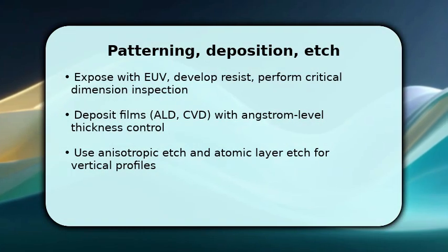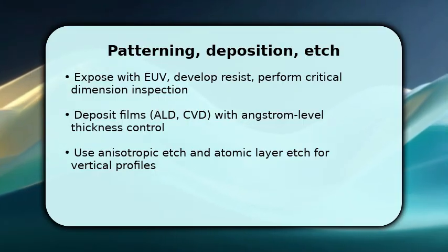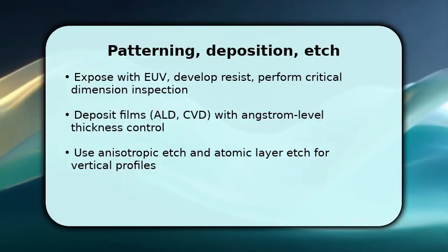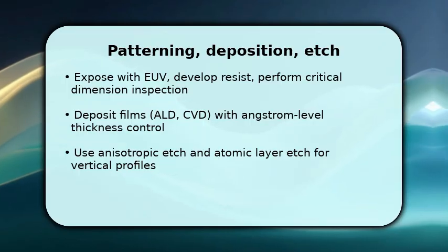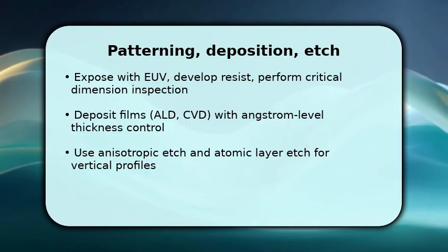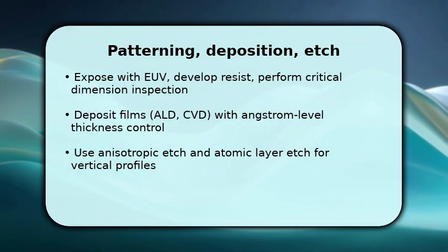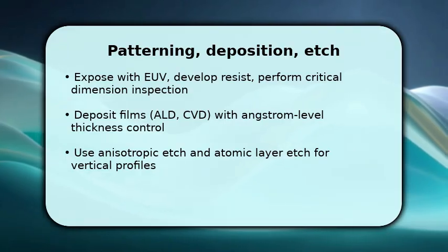You now expose the pattern with EUV and develop the resist while monitoring critical dimensions. This is where stochastic effects appear, so verify uniformity across die. Next, deposit films using ALD or CVD to achieve angstrom-level thickness control. Accurate film stacks define transistor gates and interconnects.